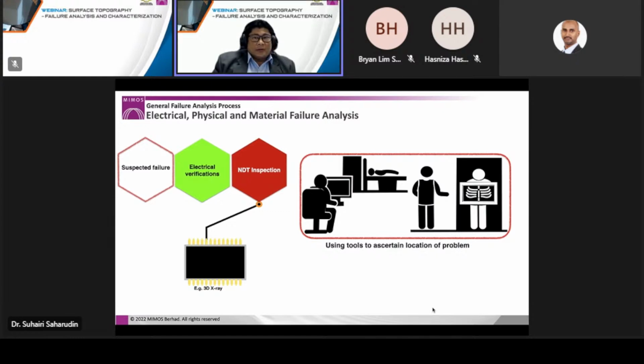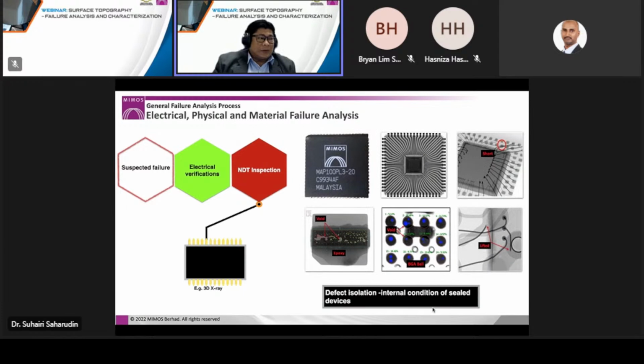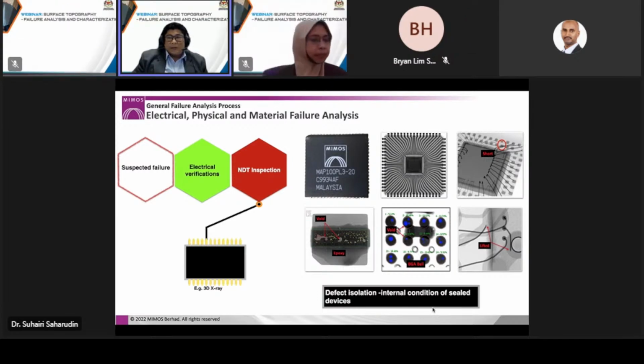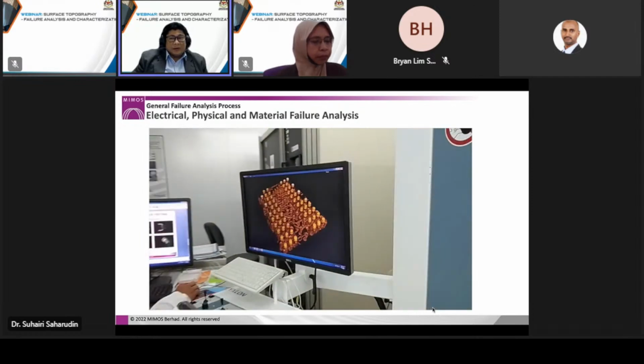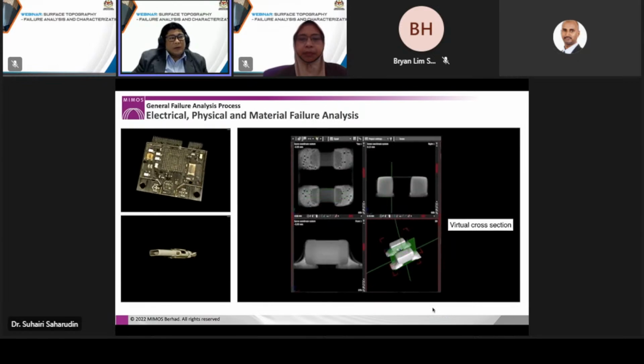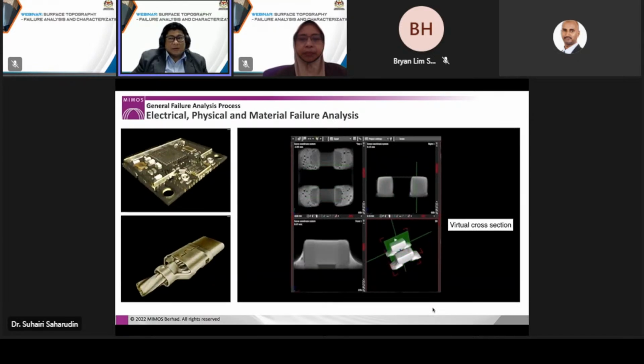For conditions where the structural integrity of a device cannot be compromised, for reasons such as it being evidence in a dispute case, a non-destructive method of defect isolation can be employed, for example using X-ray imaging. From X-ray imaging we can identify visible faults such as shorting of wires, lifted wires, or even the percentage of voids in BGA balls. Additionally, we can also use 3D X-ray imaging to reconstruct a 3D virtual cross-section view inside the failed device without damaging the package.